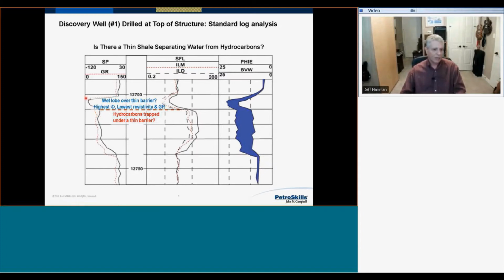We have a gamma ray, and we see at the very top this lobe that is the cleanest. It is the lowest gamma ray and most negative SP deflection, which we normally interpret as clean. It has the lowest resistivity, and again, the deep induction is less than the medium, which is less than the SFL. And there's a porosity interpretation in which this is the highest porosity anywhere within the sandstone interval.